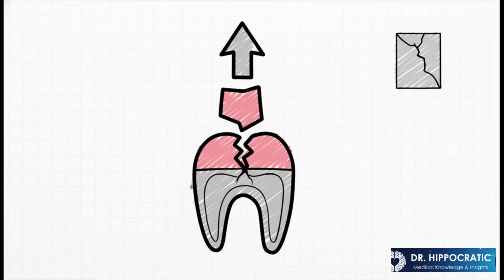The material's own internal strength is actually lower than its bond strength. So when you put pressure on it, the bond to the tooth holds on tight, but the cement itself cracks and breaks from within. This is called cohesive failure. Think back to that sticker analogy. The glue on the sticker is great, but the paper of the sticker is weak, so it just tears in half. That's what's happening here.